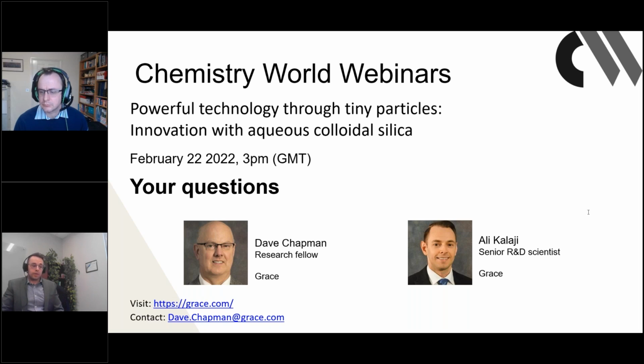There's a lot of very neat chemistry involving silane reactions with the silanol surface of the colloidal silica. And you can imagine that you can add all sorts of organic functionalities. You can add hydrophilic polymers, carboxylates, sulfonates, amines, all sorts of additional functionalities can be added, and those are in development.